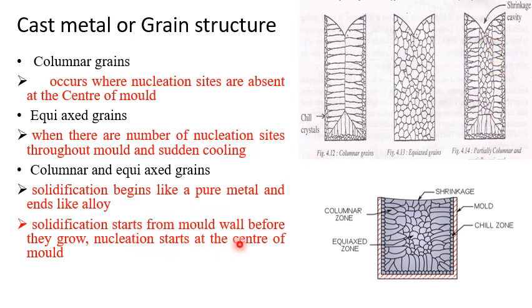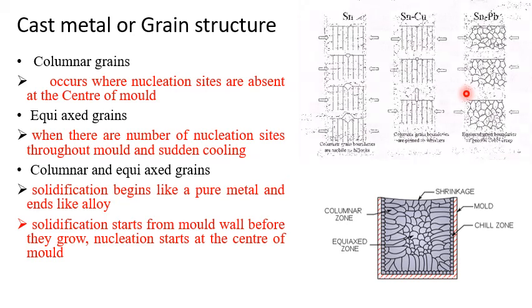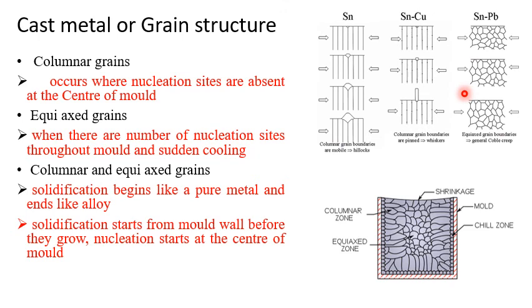So solidification starts from the mold wall, and before they grow, nucleation starts at the center. This means the nucleation is going to occur all around at a time, at the mold cavity as well as at the center. When these equiaxed and columnar grains encounter each other, the solidification is going to freeze, and we are going to get a mixture of equiaxed and columnar grains. You can see it here, the way in which we get the different types of grains.